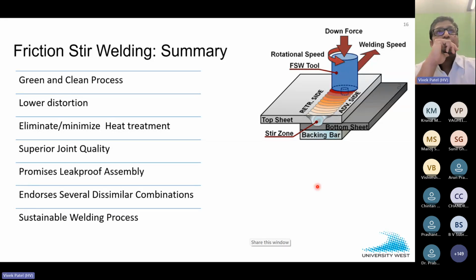In summary, I try to put summaries: a green and clean process, low distortion, superior joint quality. Then you can minimize the heat treatment in most of the cases. And this is one of the important applications that it is now addressing: leak proof. Friction stir welding provides a leak proof guarantee, I would say, when you are going to weld cast aluminum alloys. Due to that characteristic, there are several applications to build or develop different heat exchangers made of aluminum and copper, heating and cooling plates. So a lot of heat transfer or heat management devices are being investigated to be welded by friction stir welding now.